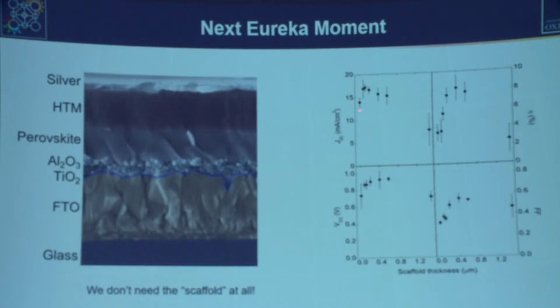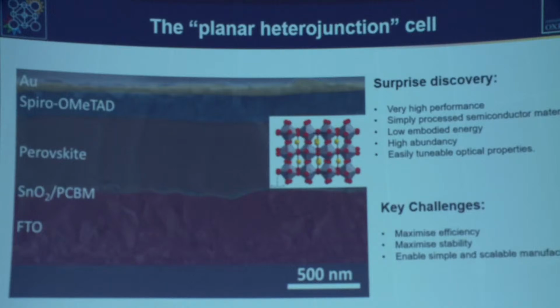Until at some point it dropped down again. So we took it to the logical conclusion, got rid of the scaffold, and found that if we could optimize the growth of these thin films, we'd get really well-performing cells. So this is the structure, pretty much the structure of devices today.